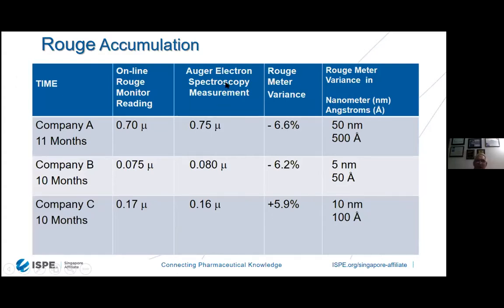But the Auger electron spectroscopy, when they took it out and ran it in a laboratory, showed virtually the same at 750 nanometers. Point is that it was very good variance between the two and correlation between the two different technologies. Company B, though, you can see we ran it for 10 months and they only had 75 nanometers accumulation, and the Auger showed 80 nanometers accumulation.